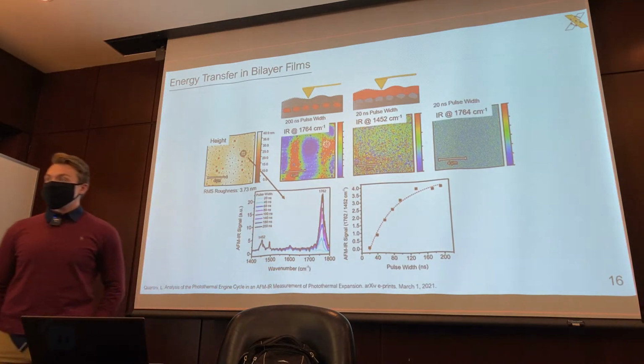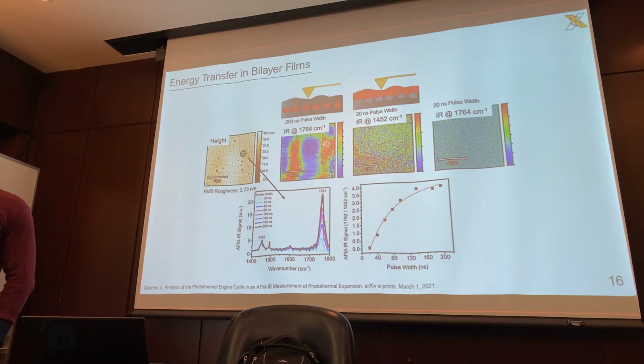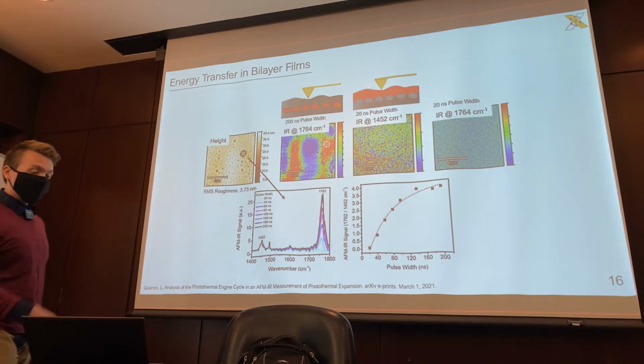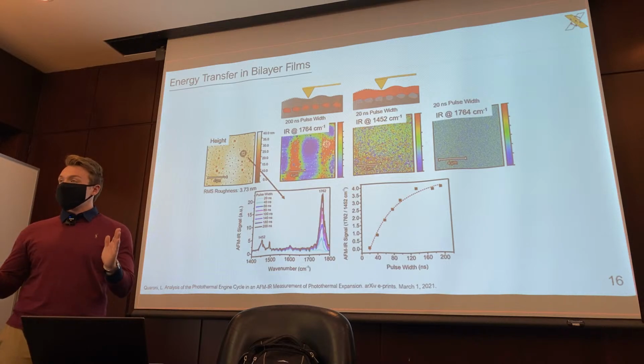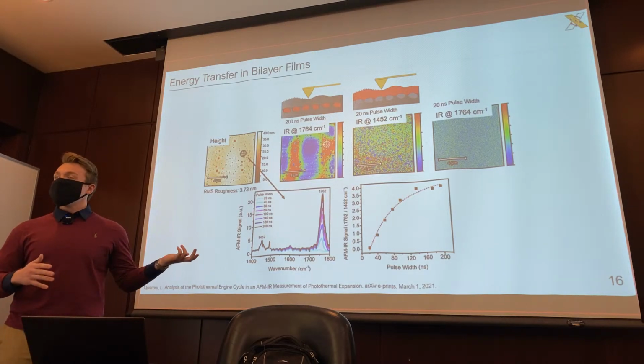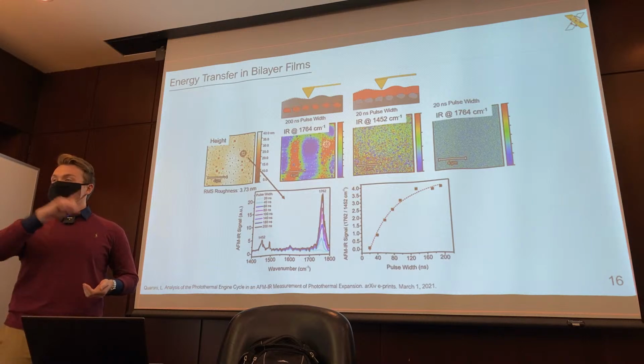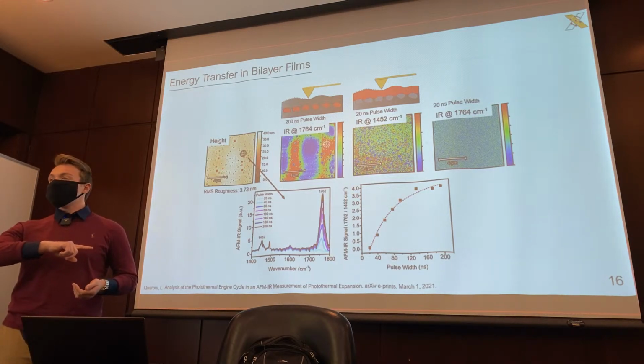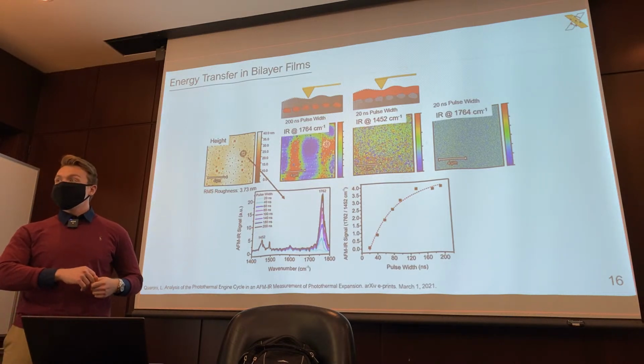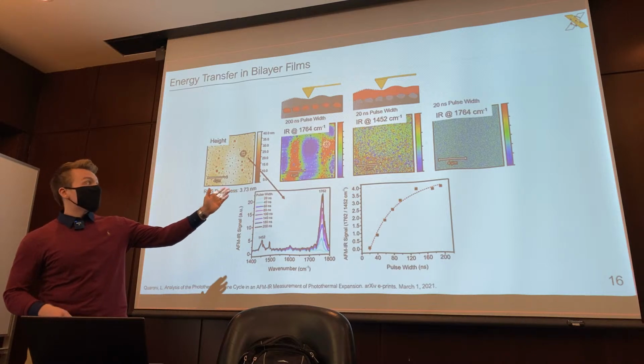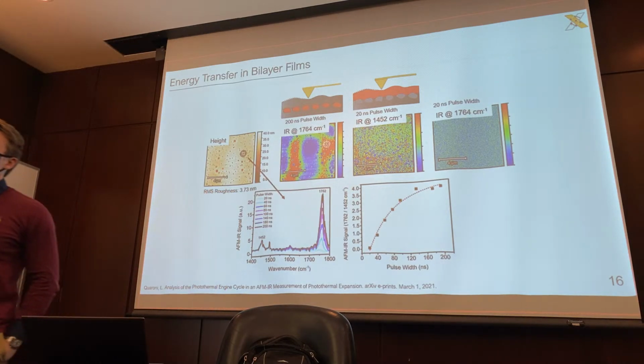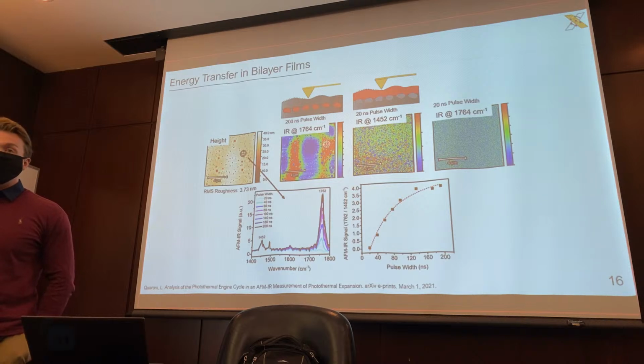Okay. And does that imply you always want to use the longer pulse width? The deeper you want to go into your sample, to get the maximum response in terms of thermal expansion, you want to use a longer pulse width. In our case, we were actually trying to achieve surface sensitivity. So using this rule of thumb, we reduced it down to 20, and these are the results that we saw. We could still see the polystyrene, but we lost track of the PLA buried underneath. Okay. So I saw this and said, wow, this really works with some of the work that we've been doing.